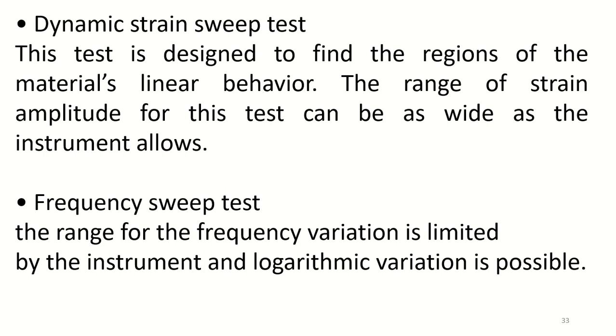Looking at the dynamic strain sweep test result, a strain amplitude value has to be chosen from a linear region. Again, the range for the frequency variation is supposed to be limited by the instrument, and logarithmic variation is possible. In general, frequencies lower than 0.1 Hz are not recommended since they are more time consuming and do not hold any practical advantages.